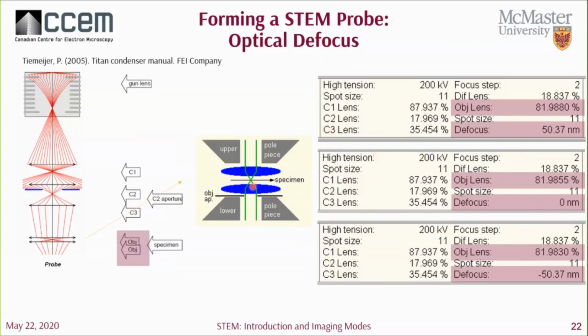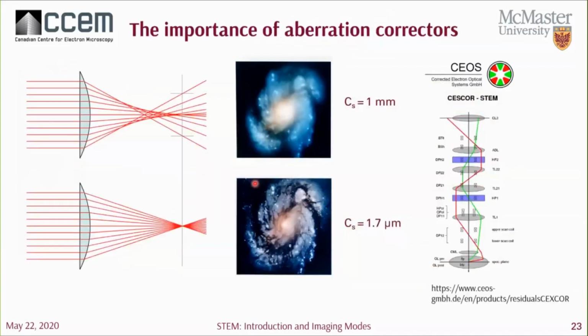Just a note, adding a little bit of defocus can help compensate for the phase shift in the probe due to spherical aberrations. And this leads us into the discussion of aberration correctors. Much of the resolution in a microscope is generally limited by aberrations in your lenses and the probe forming aperture. Spherical aberration, as you probably already know, arises from the greater demagnification towards the edges of the lens. Here, towards the edges of the lens, you have more of a demagnified image, and so this results in a crossover point on the optical axis that is not located on the image plane. This gives you the spherically aberrated disc, which can be described by the spherical aberration coefficient Cs.